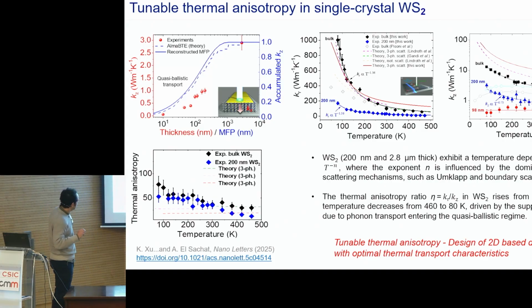And which kind of material is that? This is tungsten disulfide. And the tungsten disulfide has larger thermal conductivity. The intrinsic thermal properties are much better than the others. For example, the bismuth selenide and the molybdenum disulfide have much lower thermal conductivity in general. So the variation with the thickness is expected to be smaller.